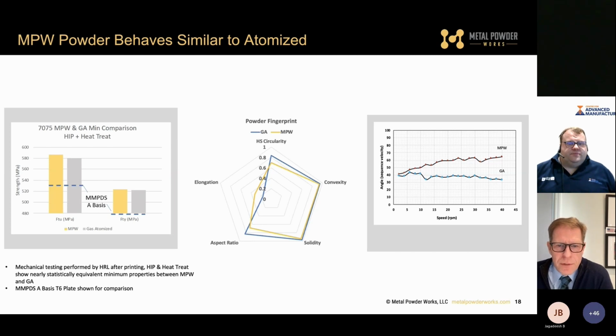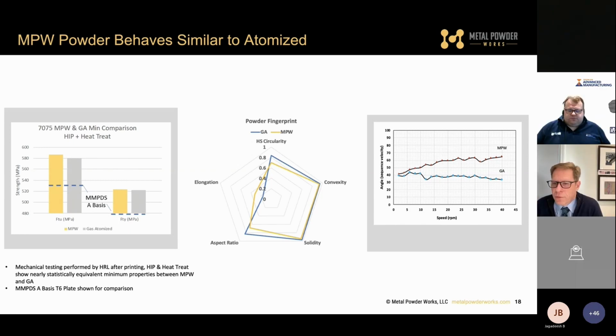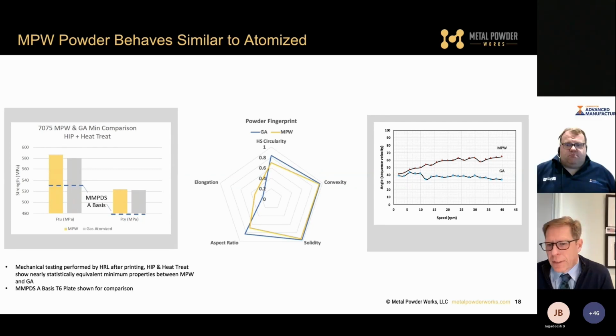If you look at the center picture, this is just a powder fingerprint that Purdue looks at. At the bottom line, you're looking at the blue lines and the gold lines, pretty much the same. It's not identical, but it basically processes the same in a lot of different metrics. And on the right, we show the rotating drum. We see some separation as we move to higher rotating speeds, which would be akin to a recoater blade. But with feedback that we've gotten from some people, we found that the faster we recoat, the better performance we got. The bottom line with this graph is that 20 degrees of difference really isn't meaningful in terms of powder behavior. It is academically different, but maybe not meaningful.